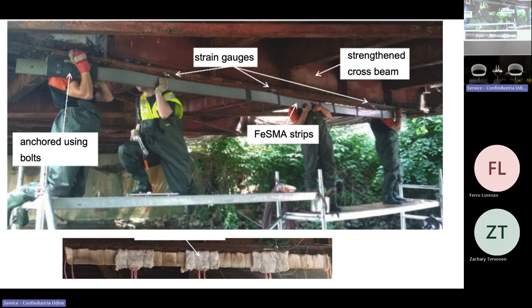So this is the shape memory element being placed in location. And then you put the ceramic heating blankets to get it to 260 degrees centigrade. And therefore, it will reverse the transformation, right? And in this case, the transformation is from austenite, which is face-centered cubic, to hexagonal close-packed epsilon martensite. But this is a real civil engineering application which puts a compressive stress on the beam, and the bridge is able to perform.